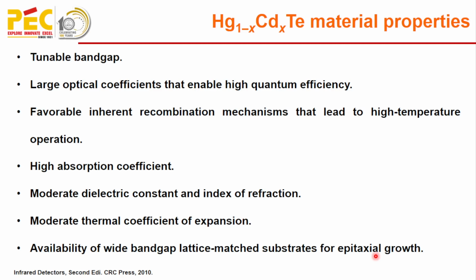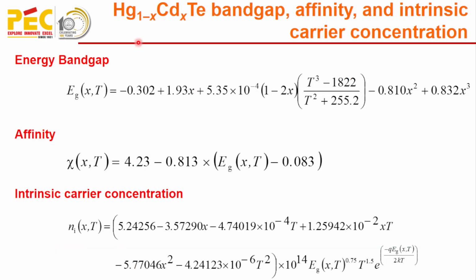Now, the energy band gap, affinity, and intrinsic carrier concentration of mercury cadmium telluride depend on the x composition of the cadmium and temperature. Depending on the cutoff wavelength and temperature, we can tune the band gap of the mercury cadmium telluride by changing the mole fraction of the cadmium. And cutoff wavelength is defined as the wavelength at which the response of the device has dropped to 50% of its peak value.